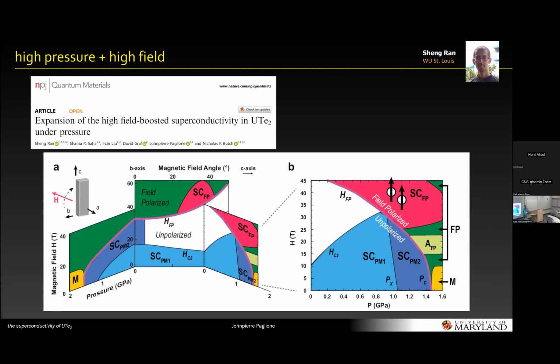Sorry. Yeah, so the direction in which there's a node, can you tell me A, B, C, which direction is that? B1U is C, B2U is B, and B3U is A. So B2U is a B-axis node. Nodes along the B-axis. Remember, that doesn't match with the penetration depth data, for instance. So then you're not able to reconcile these. No, what I would say is, and I'm an ultrasound guy too, so I would take ultrasound over any of these experiments. Yeah, in that, if there was a sizable component, there should be a shear. It's just a thermodynamic relation. There should be a jump in the shear response.